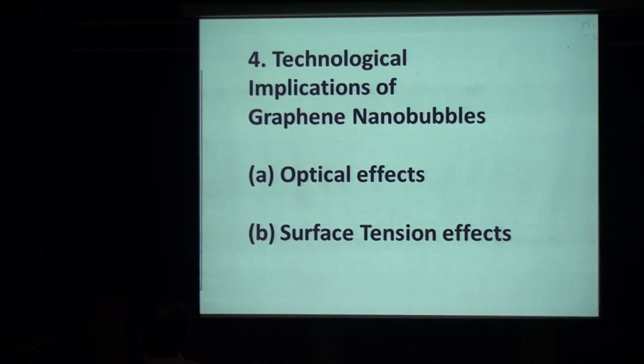In fact, this graphene is a very interesting photonic material because of 2 effects. One effect is the saturable absorption. Now, when you increase the laser intensity on the graphene, it initially absorbs the light. At some point, the absorption becomes saturated because of Pauli blocking, and then the material becomes transparent. So you have the absorptive, opaque state and then the transparent state. This can be used as a basis of optical bistability. Another effect is the optical Kerr effect. Now, this material can have an intensity-dependent refractive index change. This second effect is also useful in optical bistability.